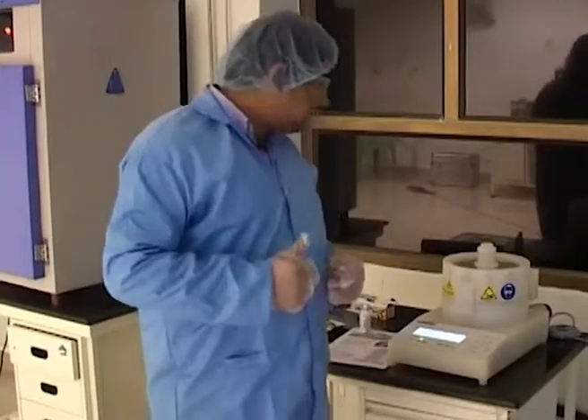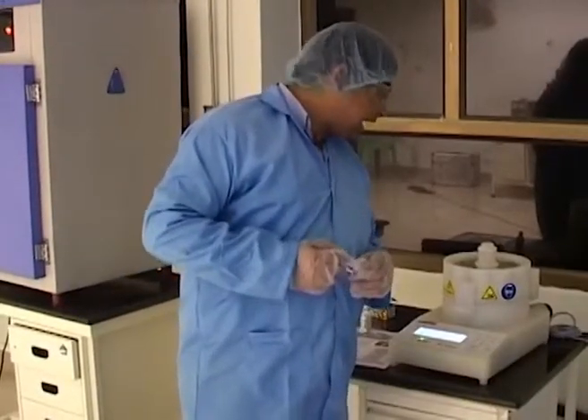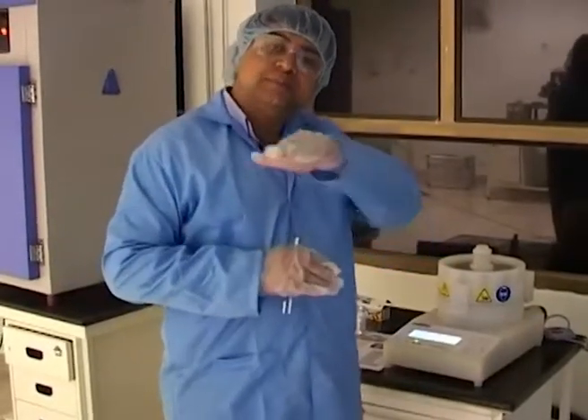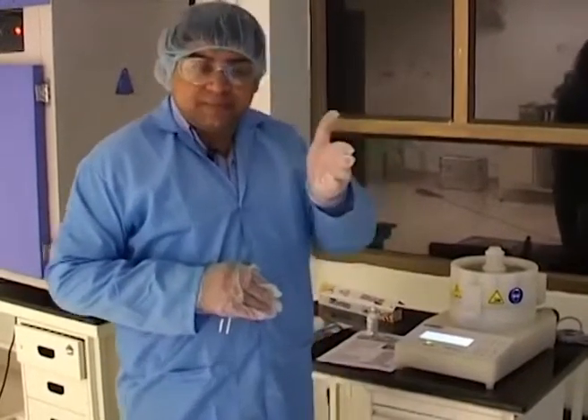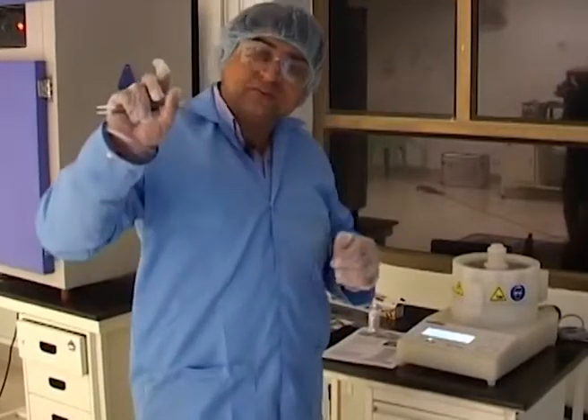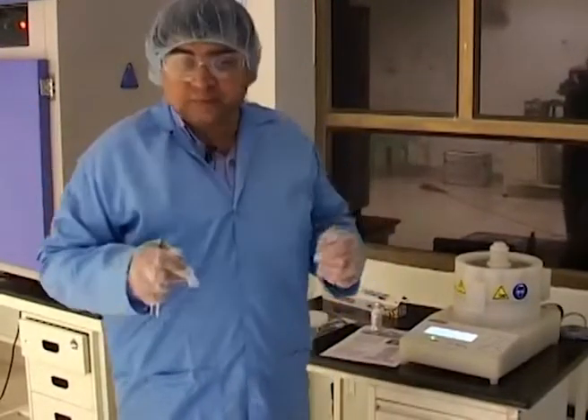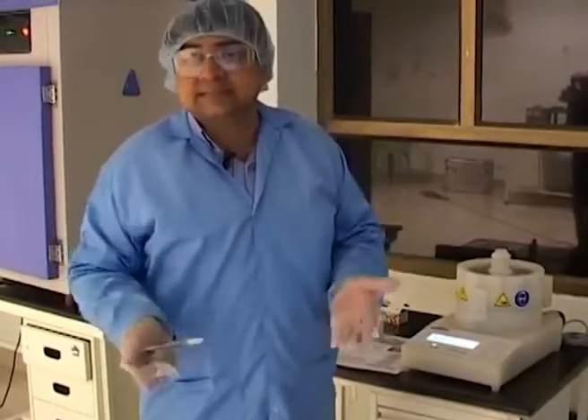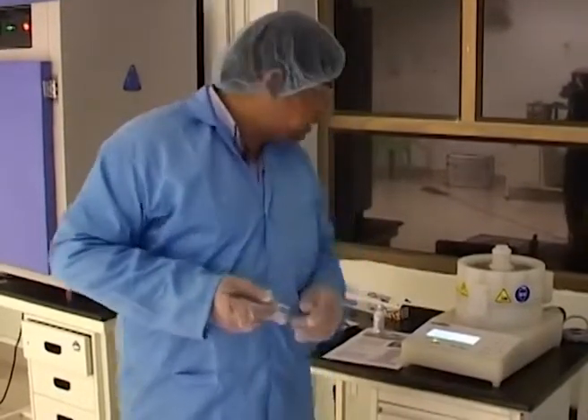Also, we need to ascertain one basic fact, that the table that we are using for keeping or aligning our hot plate should be perfectly parallel to the ground, because otherwise there may be a possibility of the resist running to one side, thus creating a thicker film at one end, which is highly undesirable, because we want uniformity in the film thickness, which also determines the sizes and nature of our structures and features.